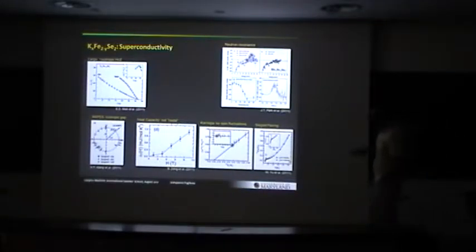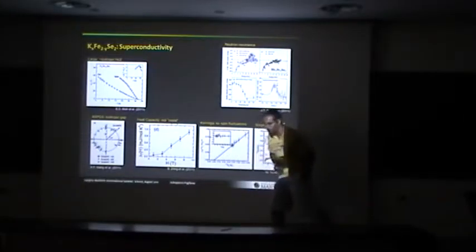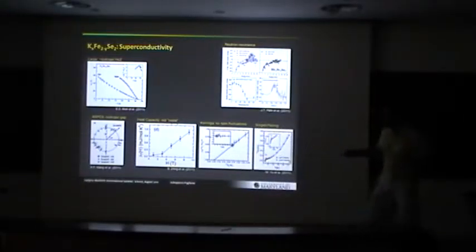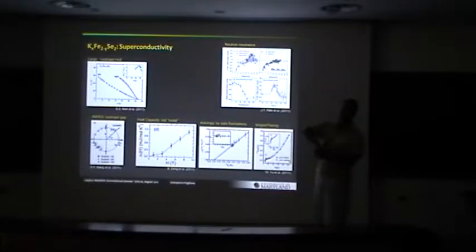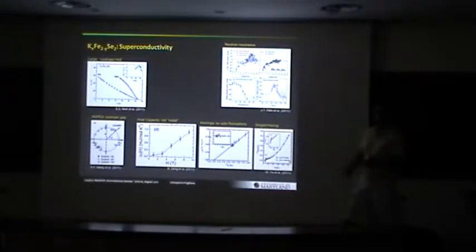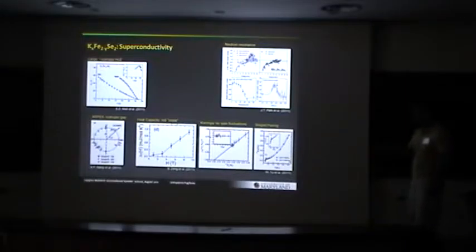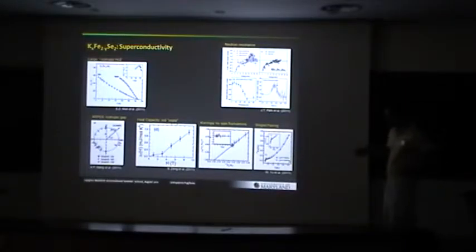The specific heat data here shows the residual gamma as a function of field. I'm not sure what temperature this is, I don't remember, but it does not look nodal, at least in the sense that you would expect some square root behavior. There are error bars on there and so on, but it looks kind of activated. This is quite low field.